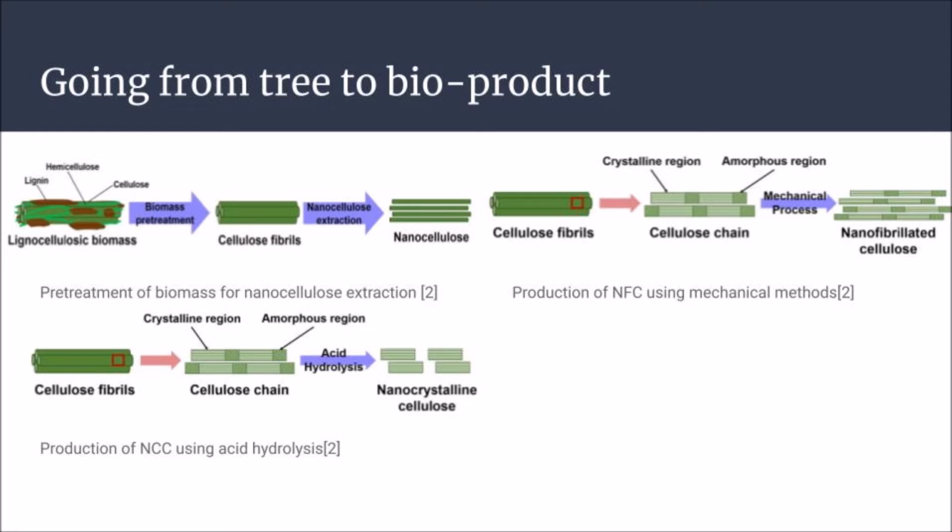However, before these methods are performed, the correct source of cellulose must be chosen. It is important to choose woods or products that have a higher cellulose content with lower impurities. After a source has been chosen, a pretreatment must be performed in order to prepare the cellulose and remove impurities like hemicellulose, lignin, and wax. These treatments break down the structures around the impurities and allow for them to be removed. The treatments can be done using either alkaline treatments with diluted solutions of NaOH or by using bleach as a pretreatment. Once the pretreatments have been completed, extraction can start.